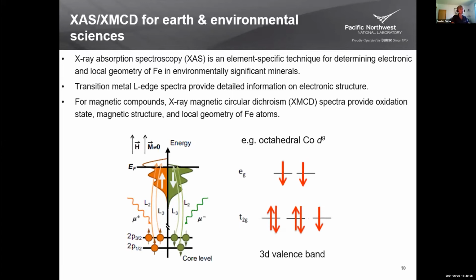And so the technique, I'll just spend a few minutes discussing how the technique itself works. It's actually a two-stage process where you first excite an electron from the 2p level of these 3D transition metal ions into the Fermi level, and the excitation depends on the type of synchrotron light that you hit it with. And so at the advanced light source, we have the option of using circularly polarized light, and the sign of the polarization will excite either the spin up or the spin down electrons preferentially.